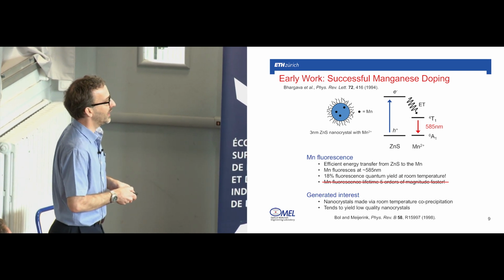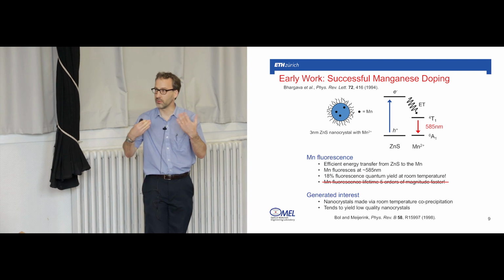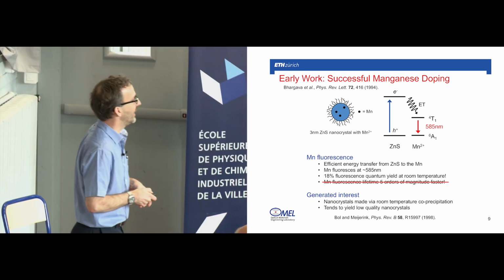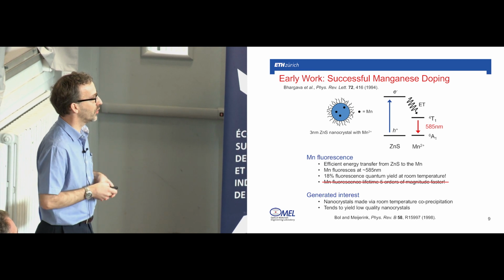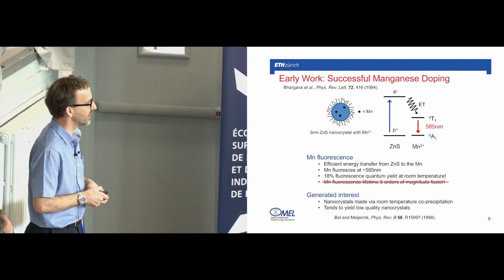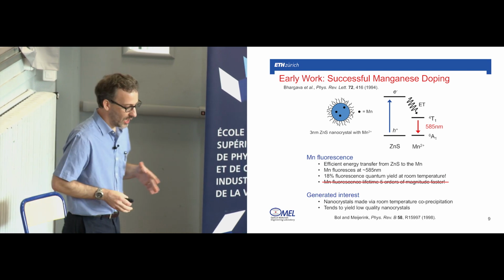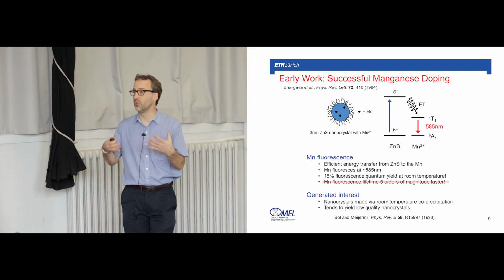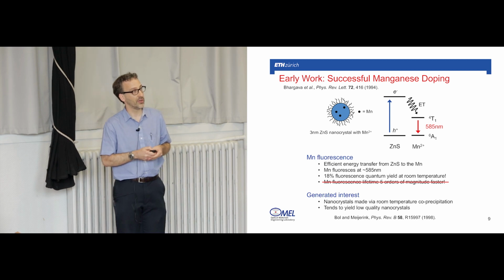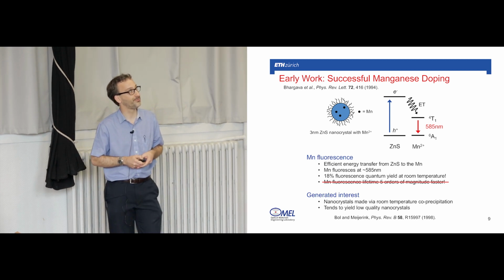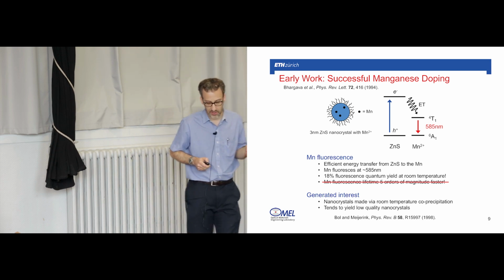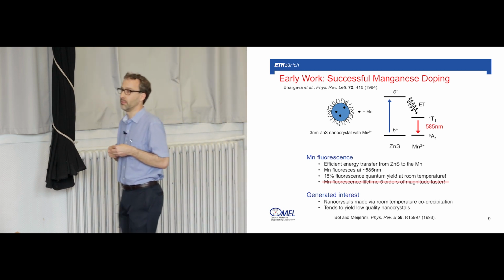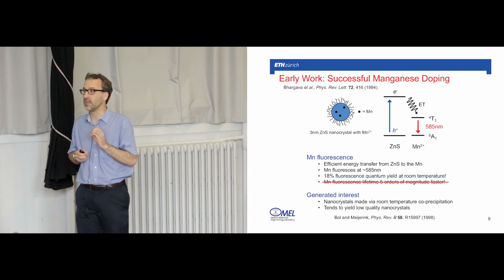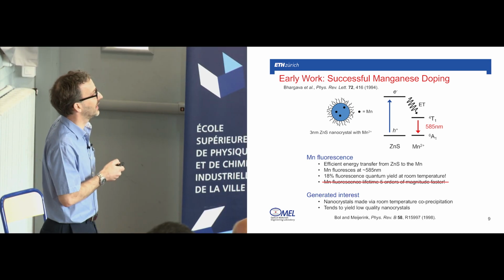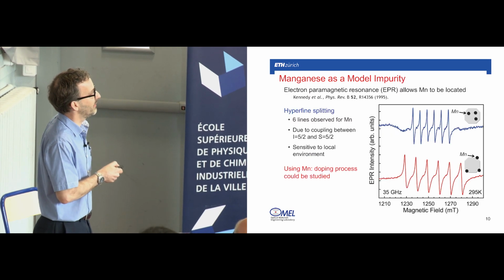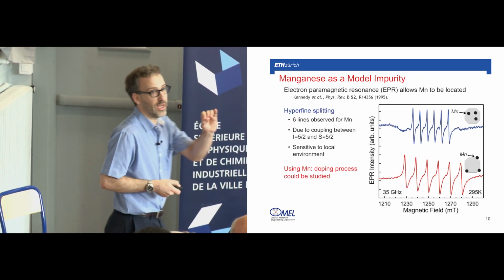But these nanocrystals were made by a room temperature co-precipitation, using a very simple synthesis. And so it tended to yield what we would call now low-quality nanocrystals. For example, it didn't photoluminesce. So the question was, can we now start applying these new syntheses that had been developed and generate even better doped nanocrystals? This led to manganese being used a lot as an impurity, and in particular a model impurity. Manganese is really nice as a model impurity because you can use electron paramagnetic resonance, or EPR, to really locate where the manganese is.